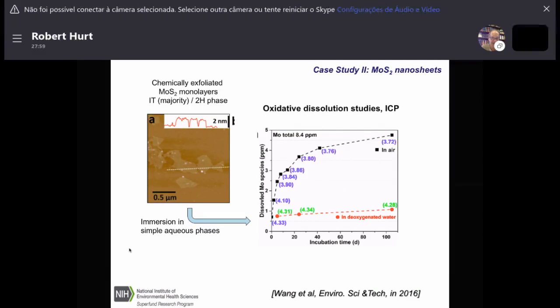Now, because 100 days is relatively long, if you breathe in molybdenum disulfide, it will exist as a nanosheet for some time. Macrophages will clear it, hopefully from the lung, but it will persist for potentially some months within those cells, possibly be swallowed as the macrophages move up the mucociliary escalator, and it becomes swallowed or otherwise removed. But in terms of long-term persistence and long latency disease formation, such as we see with asbestos, we believe this material also is not stable enough, and it's an important finding.